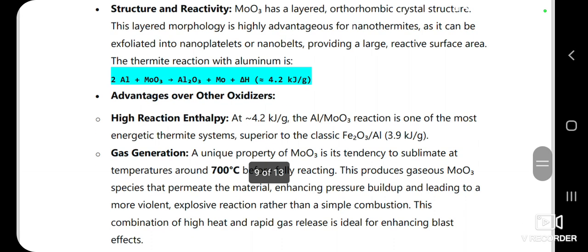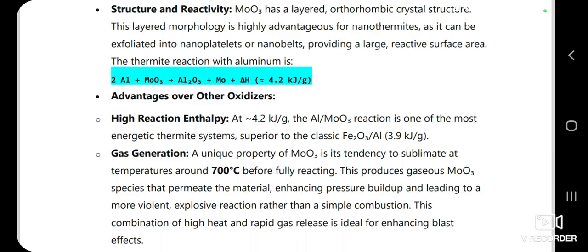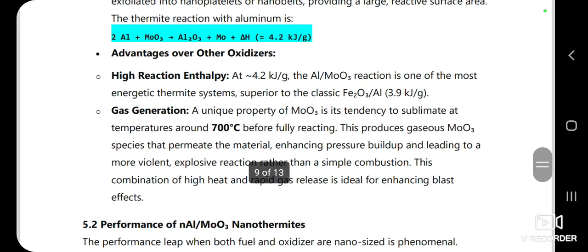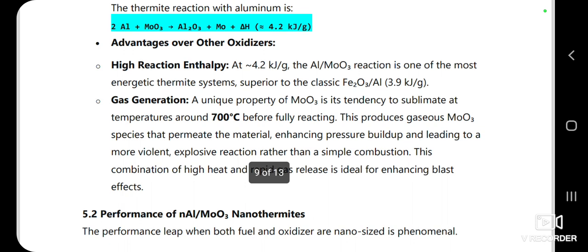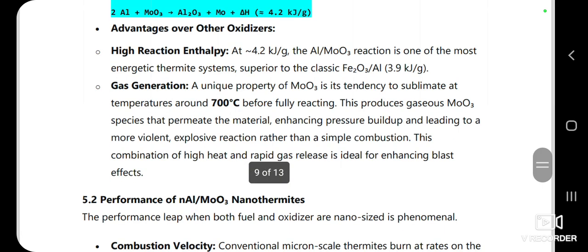Now the question is, why molybdenum trioxide? Is there any reason behind this? First, it's incredibly energetic. At ~4.2 kilojoules per gram, it's one of the hottest thermite systems. And the second is it's a gas generator. It's a unique characteristic of molybdenum trioxide that it sublimes. Sublimation means it turns directly to gas around 700 degrees centigrade before fully reacting. This produces gaseous molybdenum trioxide species that permeate the material, enhancing pressure buildup and leading to a more violent explosive reaction rather than a simple combustion.